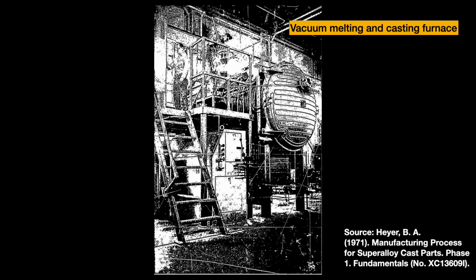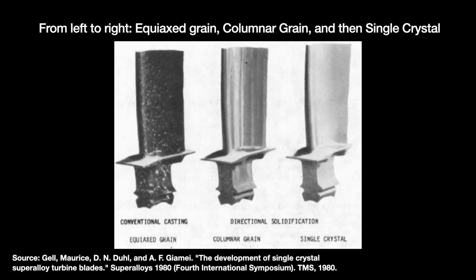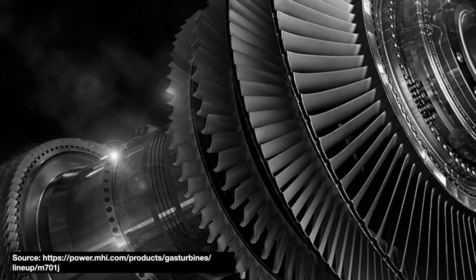I knew coming into this that these blade materials are insane, but gosh, each turbine blade is made from superalloys of nickel, plus up to 12 other elements, including one of the rarest elements on Earth. Factories then must cast these into ultra-complicated 3D shapes with internal passageways and circulating air nozzles using the lost wax casting technique. At the same time, we employ directional solidification plus pigtail to produce the blade as a single crystal. Then the single crystal blade must get its cooling air holes drilled. It must be heat treated, and then it has to get its multi-layer thermal barrier coating applied using e-beam physical vapor deposition. Then we stick it on a rotor and expose it to the fires of hell.